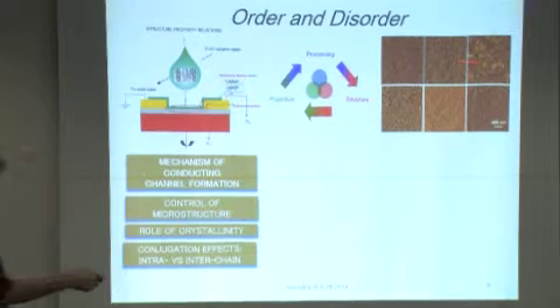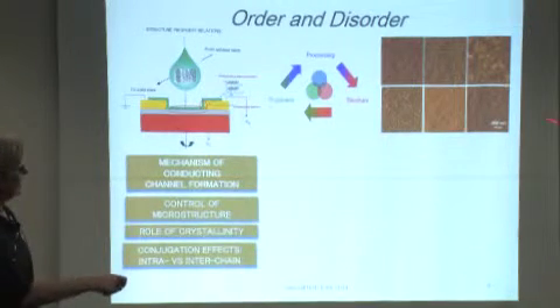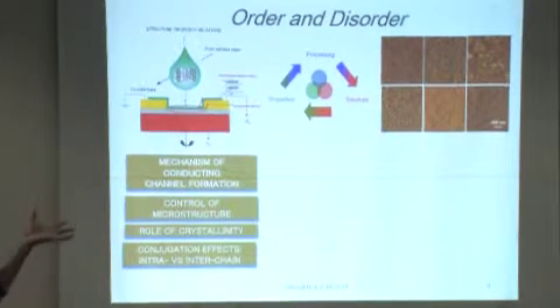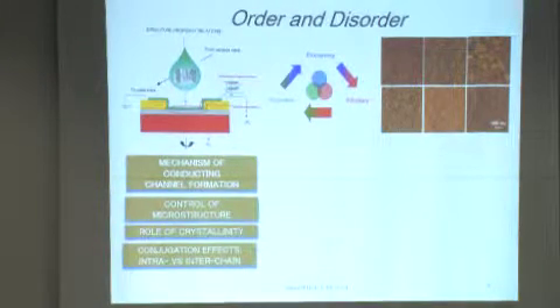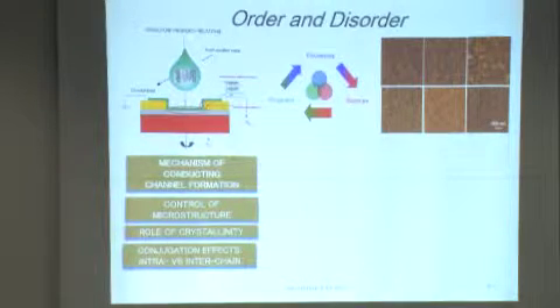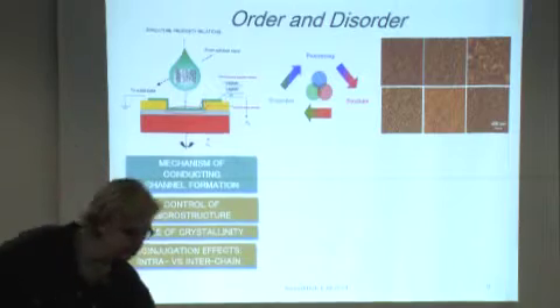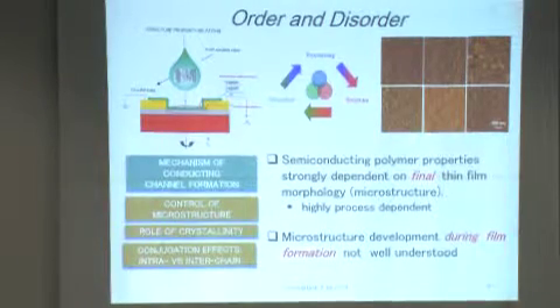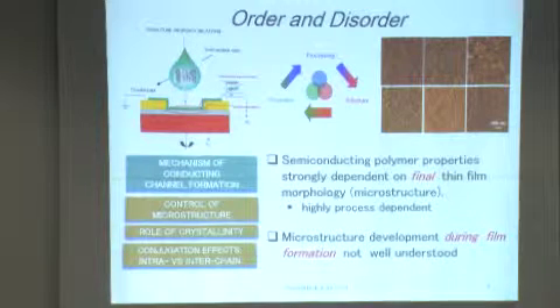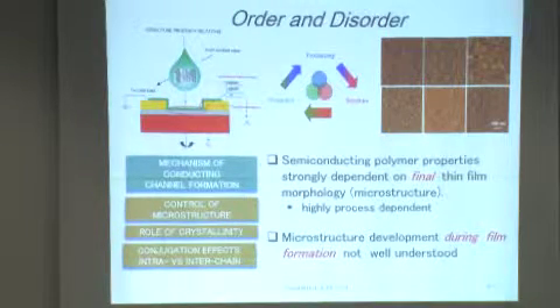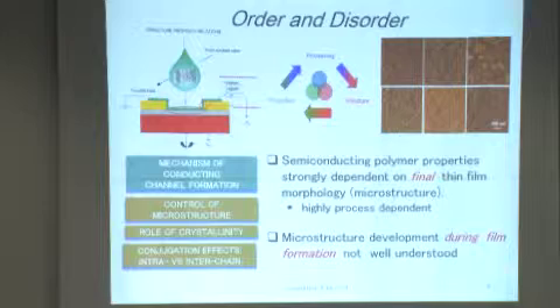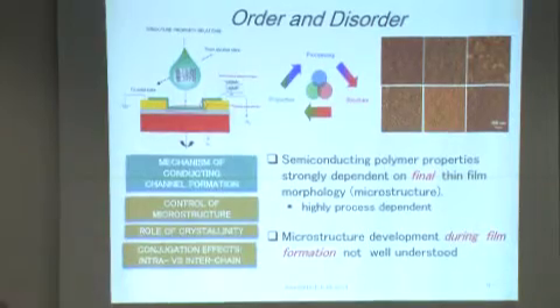You can see here 6 different AFM images, all at the same scale, 400 nanometers. Each one looks different, and each one behaves differently. And just looking at these images, there's no way to predict which one is actually better or worse. So semiconductor polymer properties are very strongly dependent on the final thin film morphology, so it's very highly process dependent, and the microstructure development during thin film evolution is not very well understood.